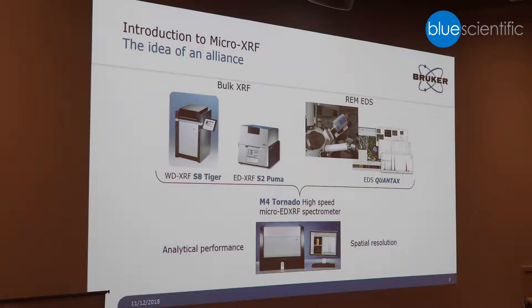Vice versa, if you do EDS analysis, you may struggle with the detection performance, because usually you're talking about 1000 PPM — detecting elements in the lower range then becomes very challenging. Micro XRF can really bridge that gap, provide a solution, and help you speed up the process, and that's one of the major benefits.